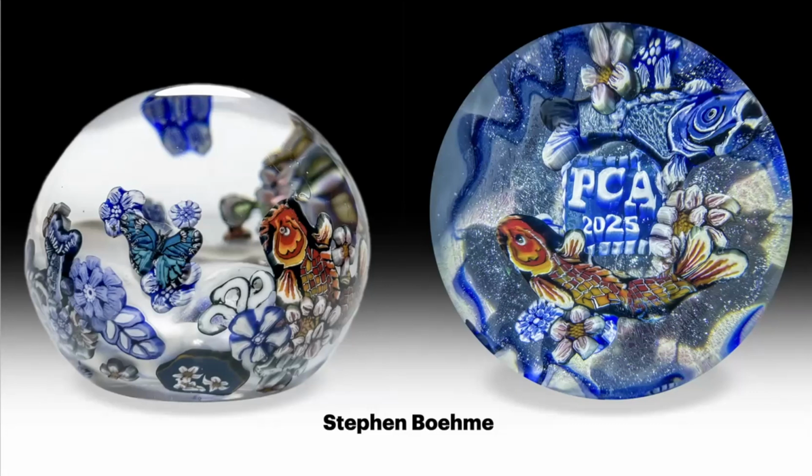They're labor intensive, these works. Each one of these murrine are composites of separate murrine. So, for instance, this fish, the head would have had to have been built out separately, annealed and then cooled, and then he would have built out the fins and the scales. All these bits and parts would have been built out separately and then brought together to make the final full figure fused together.